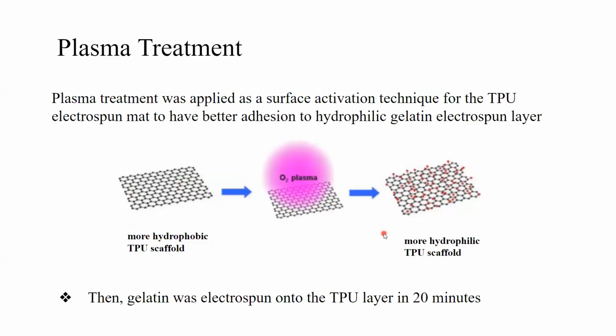As I mentioned, layer by layer electrospun scaffolds were produced in this study. But since TPU is naturally hydrophobic and gelatin is hydrophilic, adhesion problems were seen between two layers. That's why plasma treatment was applied as a surface activation technique for the TPU electrospun mat. After the plasma treatment, gelatin was electrospun onto the TPU layer in 20 minutes.